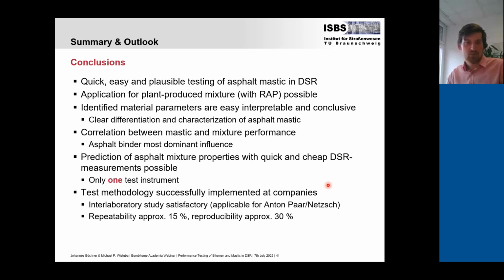Actually, the test methodology was successfully implemented at the companies, so they were kind of surprised and happy that they can try this with their own materials. We carried out an interlaboratory study, which was satisfactory. It was not perfect, but we didn't expect that because the companies tested with mastic for the first time.